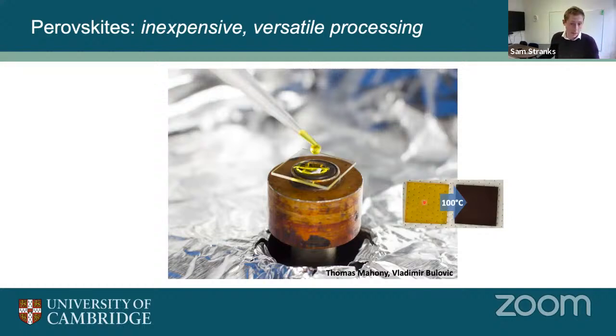So we heat them at 100 degrees Celsius, which is very low temperature for semiconductor processing. Silicon, for example, is more like 900 to 1,000 degrees Celsius or more, depending on what you're processing. So this is very low temperature, but it produces a very nice crystalline film that absorbs light very strongly. And this is the basis for the solar cells that we make.